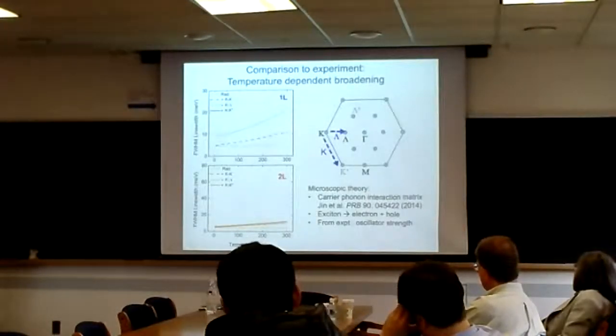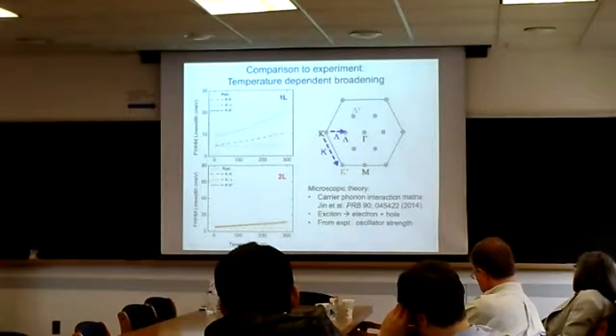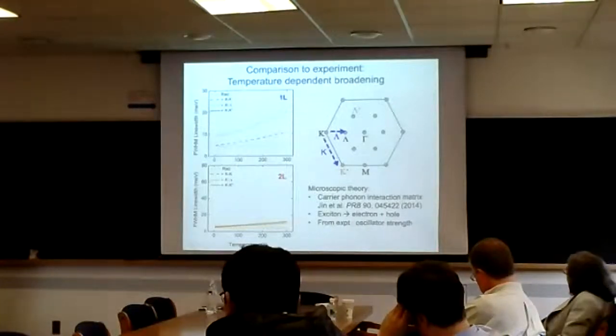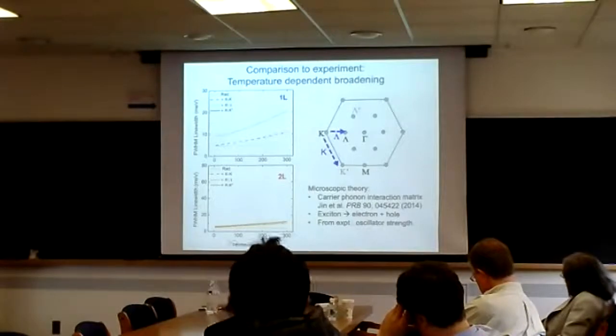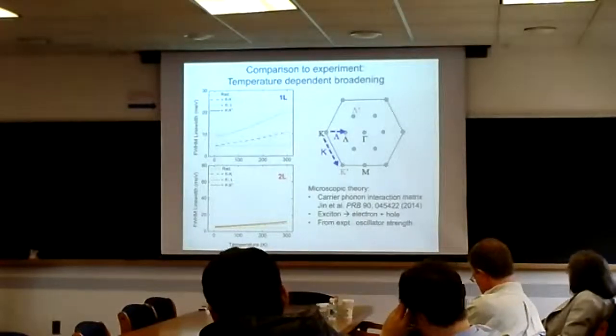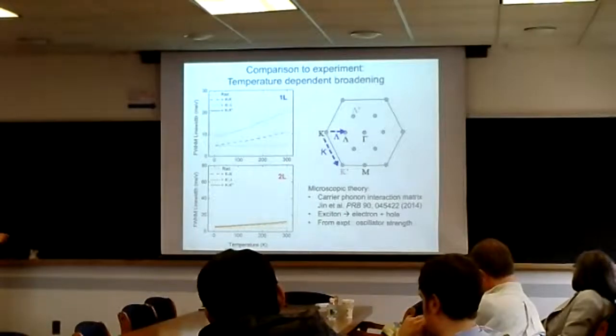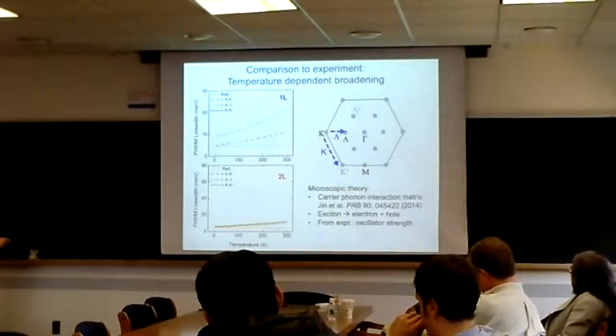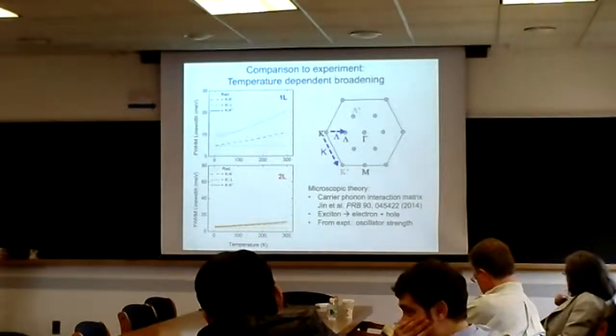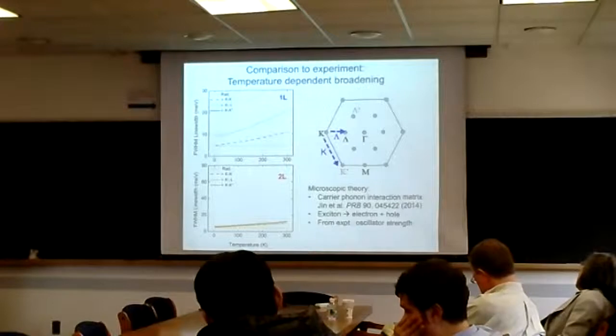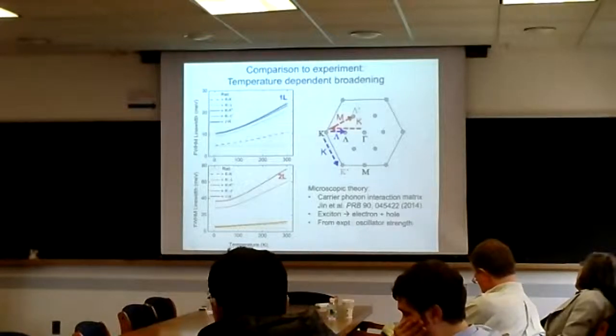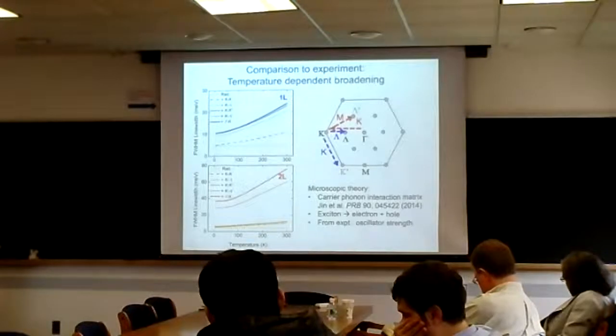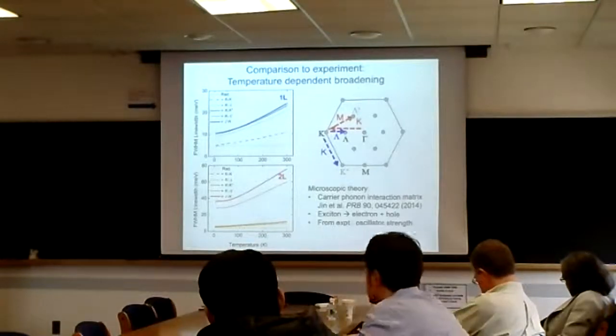On the theory side, the carrier-phonon interaction matrix elements were taken from previous work, and then the problem was solved to create these maps of the line width versus temperature. This is all pure theory. So you have the radiative rate over here, and then you add on the different scattering, K to K, K to lambda, K to K prime, and this is what it looks like. And if you add these processes that involve K to lambda prime, you get this huge increase in the line width.